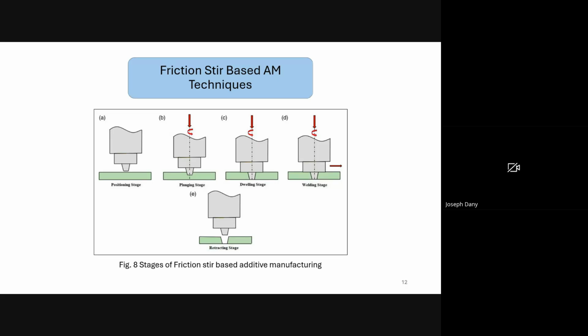There are three important functions during friction stir additive manufacturing: to generate frictional heat, to control material flow, and to keep the plasticized material beneath the shoulder. It's worth noting that in thin sheets, most of the heat comes from the shoulder, while in thicker plates, the pin plays a bigger role. Also, specifically designed shoulders and pins can improve both heat generation and material flow.